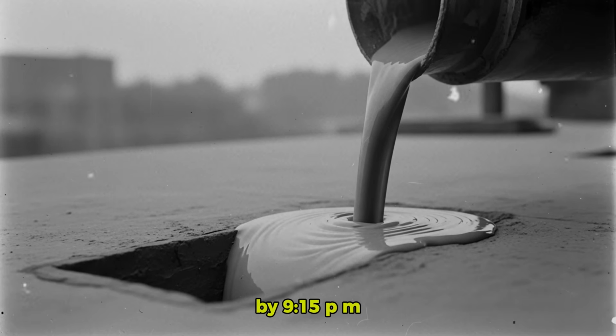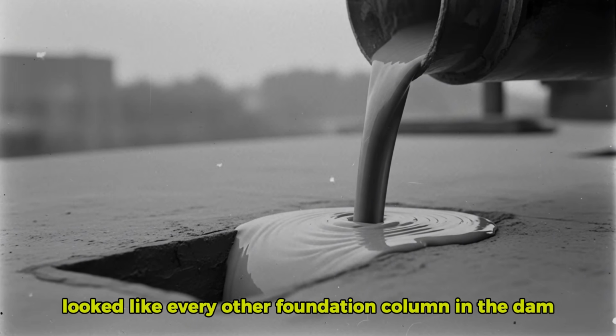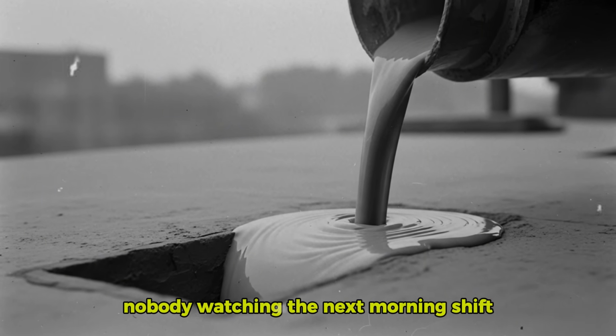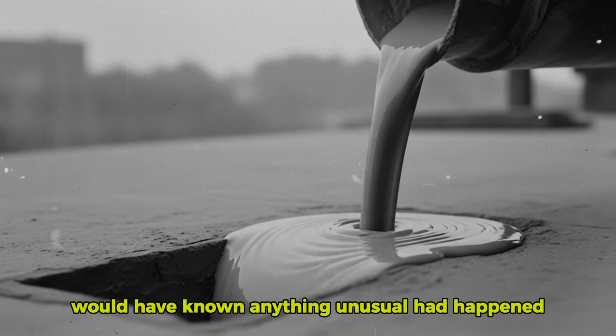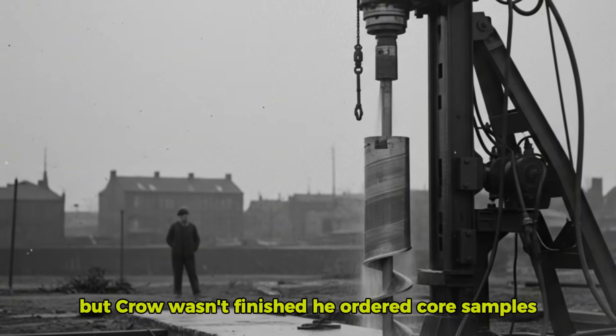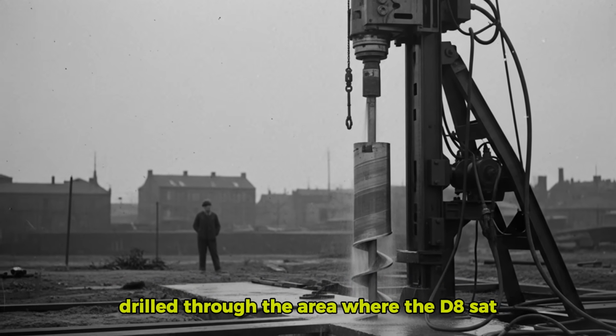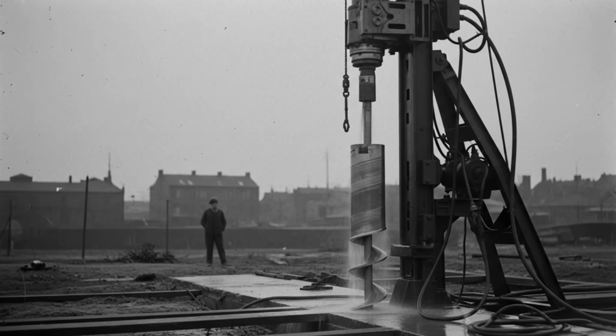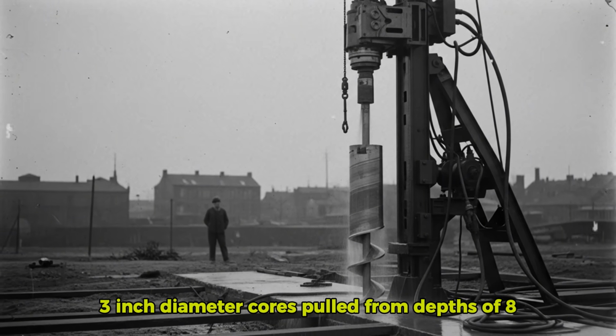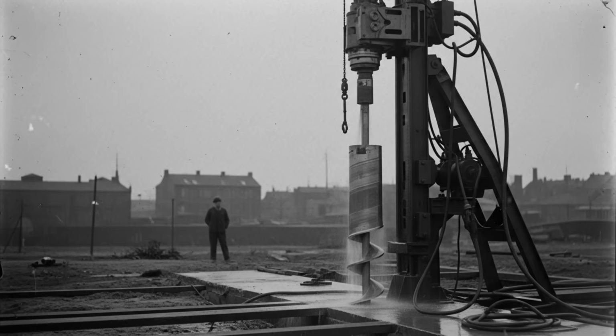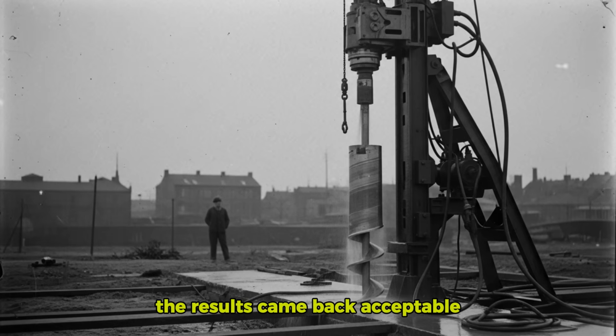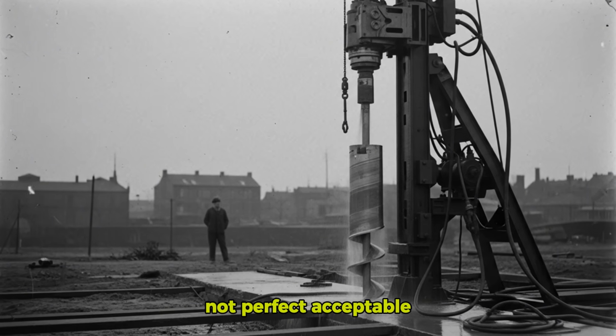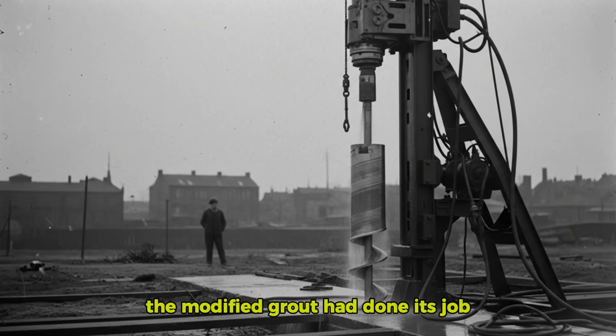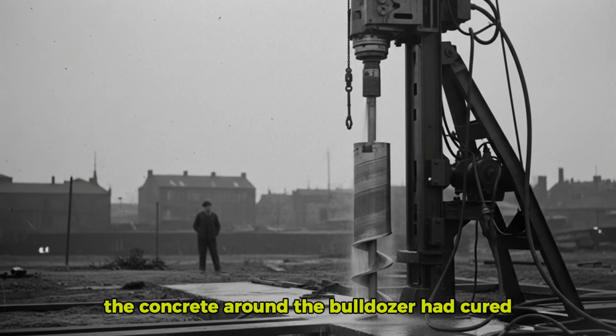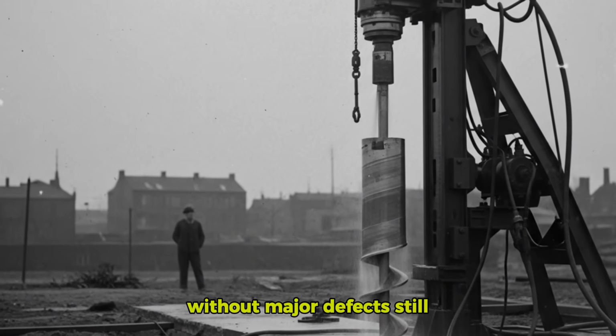By 9:15 p.m., column 47 looked like every other foundation column in the dam. Nobody watching the next morning's shift would have known anything unusual had happened. But Crowe wasn't finished. He ordered core samples drilled through the area where the D8 sat. 3-inch diameter cores pulled from depths of 8, 12, and 16 feet. The lab technicians tested them for voids, cracks, and bond quality. The results came back acceptable. Not perfect, acceptable. The modified grout had done its job. The concrete around the bulldozer had cured without major defects.